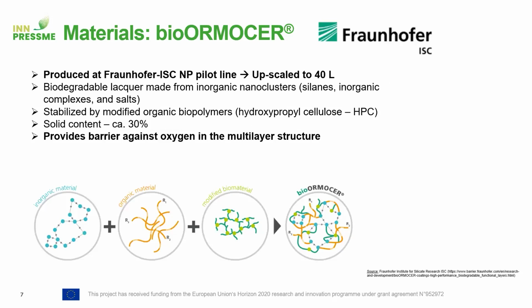And then the third component in this multi-layer was bioORMOCER from Fraunhofer. They scaled up the production of this bioORMOCER up to 40 liters. bioORMOCER is a bio-based lacquer, which is made of inorganic nanoclusters, and it is actually a very multifunctional and flexible coating. The basic components are the same, but just by a little bit of tuning or adding different components, you can get different types of functions of the material. So it can function as an oxygen barrier, which was the case here, and also, for example, give antimicrobial properties or antistatic properties to the final material. And here we use this 3-component system, which was stabilized by a biopolymer, hydroxypropyl cellulose.